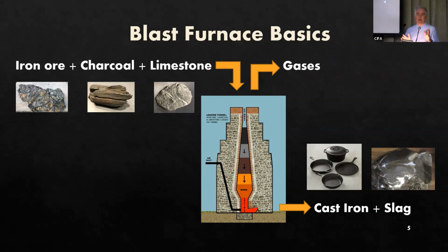And the second one is also pretty astounding. The weight of air. We don't usually think of air as being rather heavy, right? The weight of the air consumed in the furnace per ton of iron produced is about twice that of the weight of all the solid materials that are entered into the furnace. The weight of air consumed in the furnace per ton of cast iron produced from that furnace is about twice that of all the solid materials, the charcoal, the iron ore, the limestone dumped into the furnace.